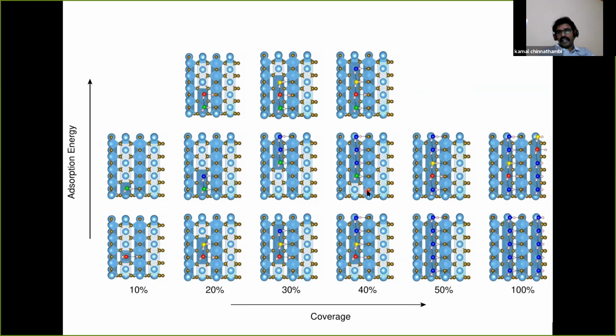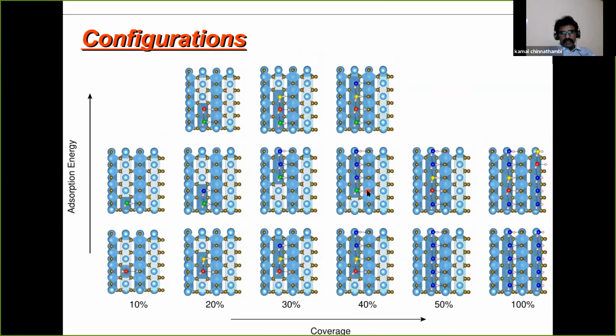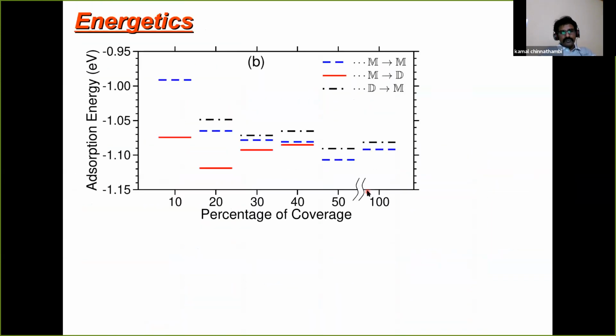For each molecule, we perform the calculations with the oxygen having a 1s electron removed from that shell. So we have several calculations, and then, using this together with the ground state calculation, we subtract the energies so that we can calculate the binding energy from this. Okay, so these are the trends for the adsorption energies.